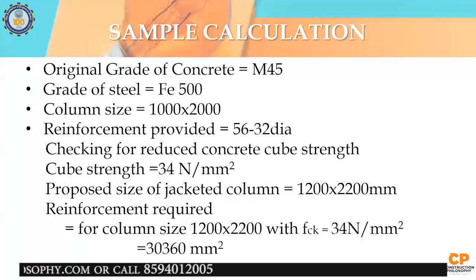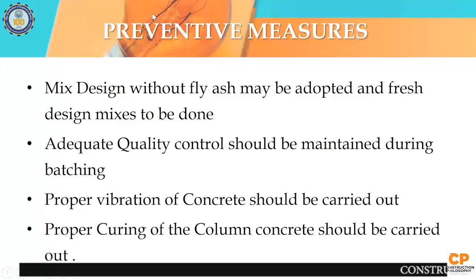So the actual condition was again put into the model and analyzed for the behavior, and based on that you increase the size of the column and make sure that the steel provided is more than what is required for the particular size, and verify that it is sufficient. So here you can see that we have increased the size of the column to 1200 by 2200, and additional reinforcement for column jacketing was made, and a mix design without fly ash was adopted and a fresh design mix was done.